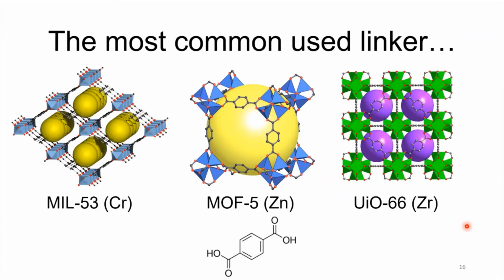We know we're going to use holmium, but what about the linker? Well, we just look at literature and it's really easy to see which one is the most commonly used linker. And it's this one down here called terephthalic acid. And here are a few examples like MOF-5, which is a zinc-based MOF, the first MOF ever reported by Omar Yaghi. A zirconium MOF, which is very stable in water, or a chromium MOF, which is one of the first reported to have breathing behavior.